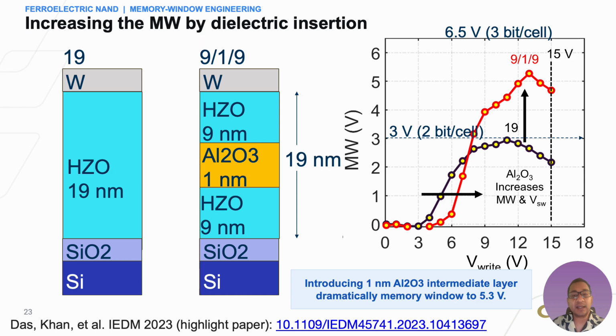The 1 nanometer dielectric insert increases the memory window significantly. The uniform 19 nanometer hafnium zirconium oxide device reaches a memory window of about 3 volts. The 9/1/9 laminated stack reaches about 5.3 volts at a similar total thickness while remaining within the 15 volt write voltage target. The insert redistributes the electric field, changes the switching behavior, and creates an internal electric field, allowing a larger threshold separation or a larger memory window.